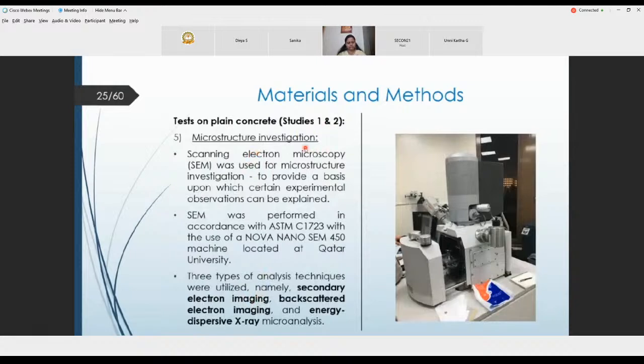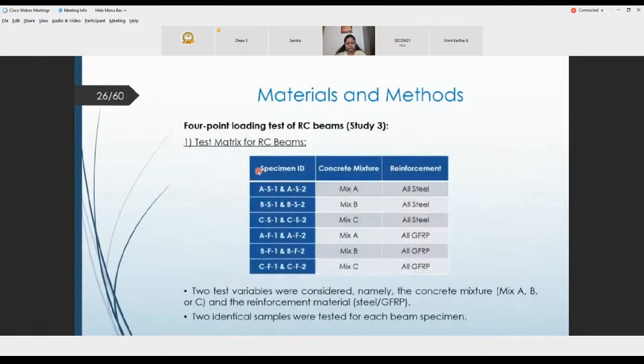We tested also the microstructural behavior of the specimens. We used the scanning electron microscopy, which was performed in accordance with ASTM standards. We actually considered 3 types of analysis techniques, namely the secondary electron imaging, backscattered electron imaging, and energy dispersive X-ray microanalysis.